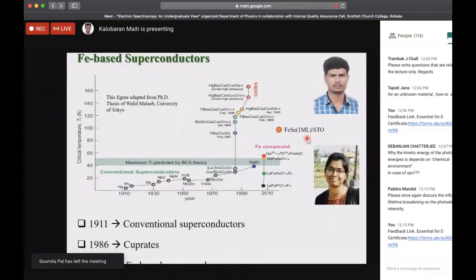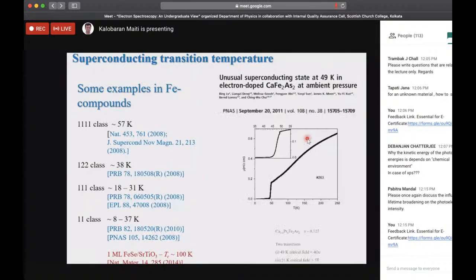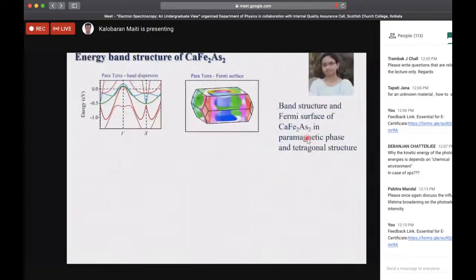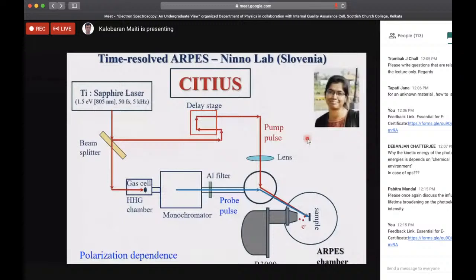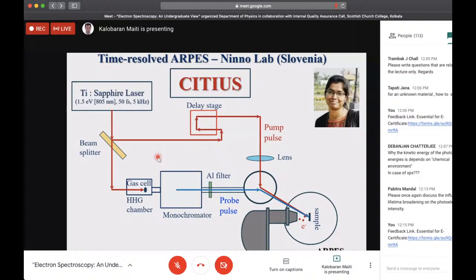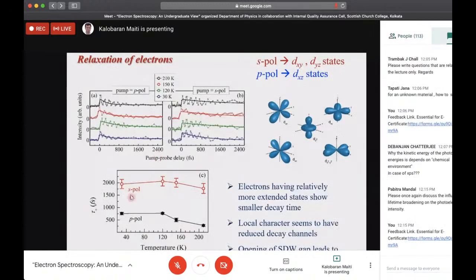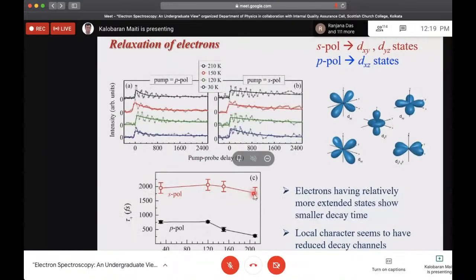Maybe I'll just say one thing in this iron-based system. You can do time-resolved photoemission to find out what is the lifetime of these electrons when you have excited them. And that gives you interesting information, which we have recently discovered. Time-resolved photoemission has been done by many groups, but our discovery is that if you use polarized light, you can actually selectively excite electrons from different orbitals that we have shown here. So, for example, if you use one kind of polarization, you can excite electrons of one type, which has a lifetime of the order of, say, 2 picoseconds, so 2000 femtosecond.